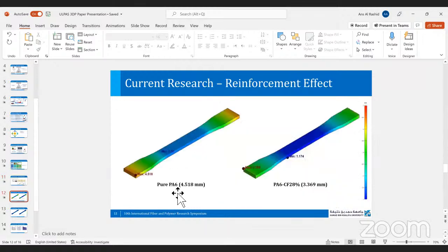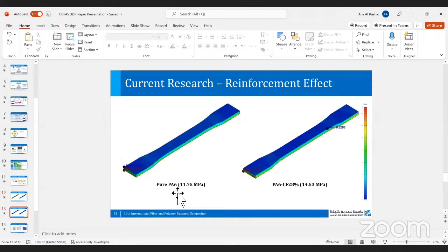Here, I'm comparing just two, where one is pure polyamide 6, and the other one is polyamide 6 reinforced with 28% carbon fiber. Once the printing is done, after the cooling, we can observe the deflections of the final part, which is very important to study when you have to print functional components. The control over the dimensions is very important. So by adding the carbon fibers up to 28%, we can reduce the deflections of the 3D printed specimen from 4.5 millimeters to around 3 millimeters.